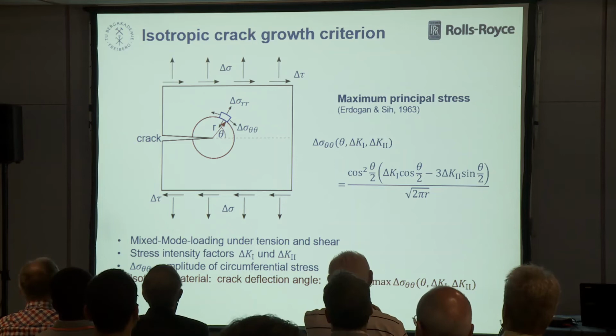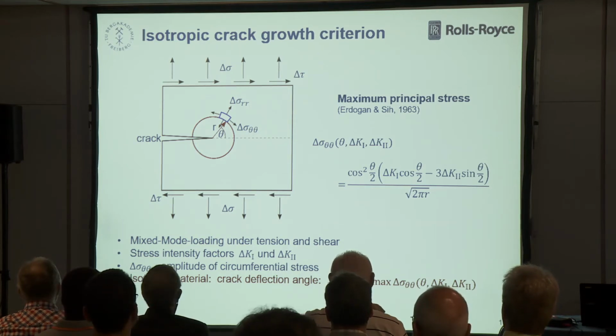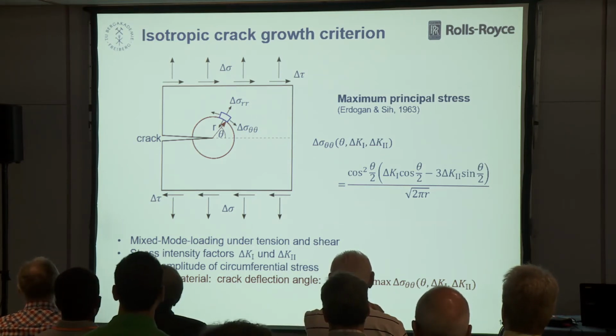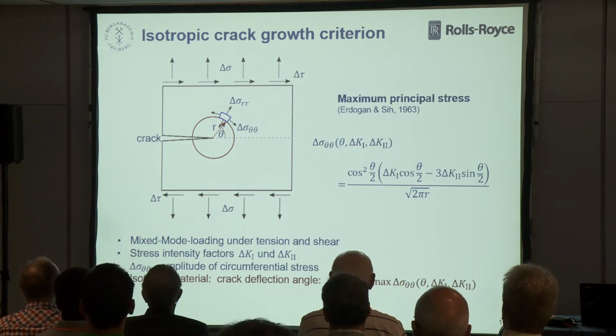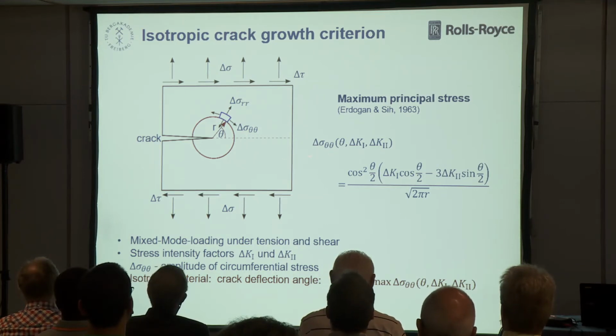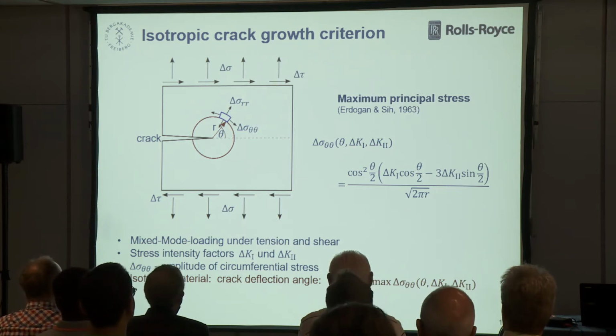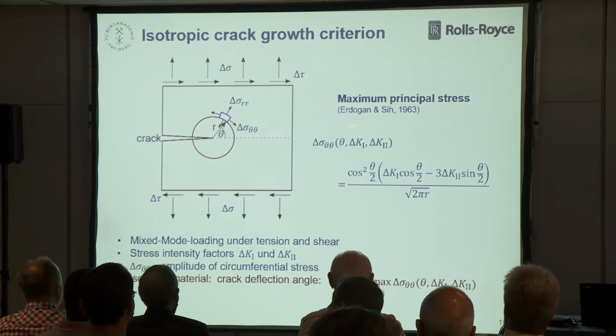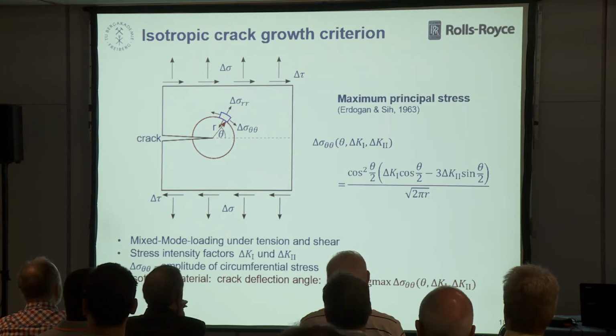So now let's come to the problem. I recap the isotropic criterion, the maximum principal stress criterion. Everybody of you knows it. In 2D, we have the circumferential stress, sigma theta theta, at a radius r around the crack tip. It can be described by the K-factors in this well-known formula. And the maximum principal stress criterion says that the crack goes in that direction where the sigma theta theta has its maximum, for an isotropic material.